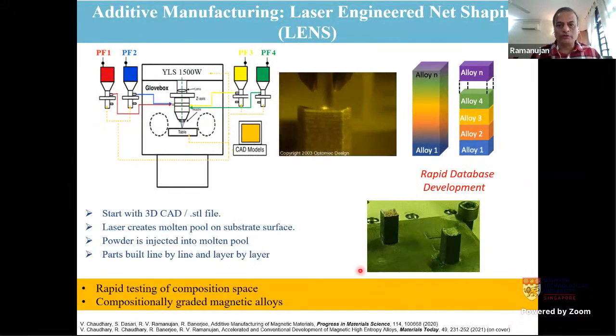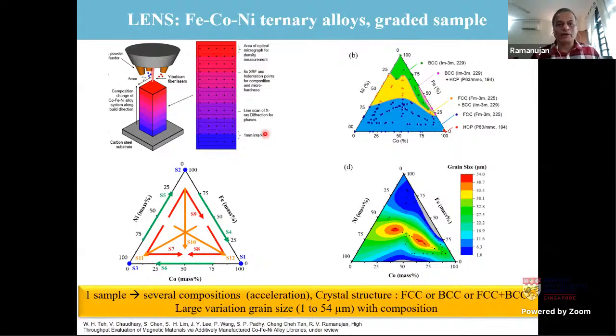So what we do is we produce samples. For example, you can see here, which are basically pillars. And these pillars, using this additive manufacturing technique, we can change the composition from bottom to top. So as you can see, a single sample contains a sandwich of many different compositions. So in one sample, you can have a layered structure, which has various compositions. And once we produce this, we can use our accelerated methodologies to study the crystal structure, for example, because crystal structure is often related to the properties.